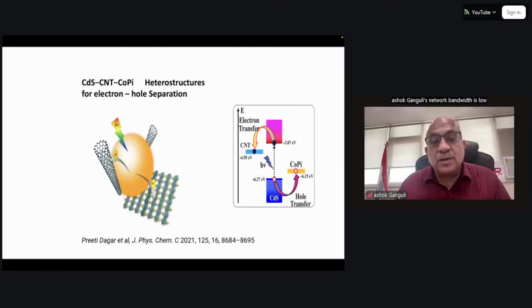So this is another example where you have a hole sink and an electron sink. And this is again like cadmium sulfide nanoparticles or supraparticles. The cobalt phosphate acts like a hole sink. It takes away holes, and the carbon nanotubes used here act as electron sink. So if the electrons are removed by carbon nanotubes and cobalt phosphate removes the holes, then effectively both electrons and holes are migrating away from the site where they are being produced by the photons. And so the lifetime of electrons and holes will be high, and so efficiency of this catalyst would be high. And that's what we see.